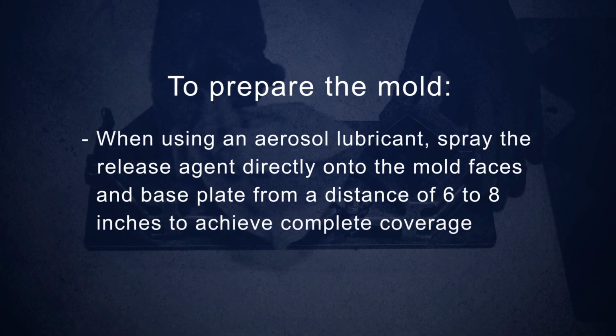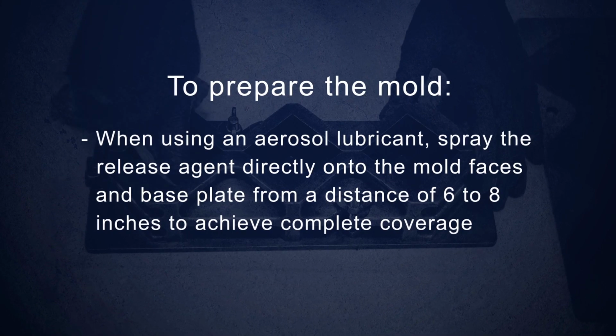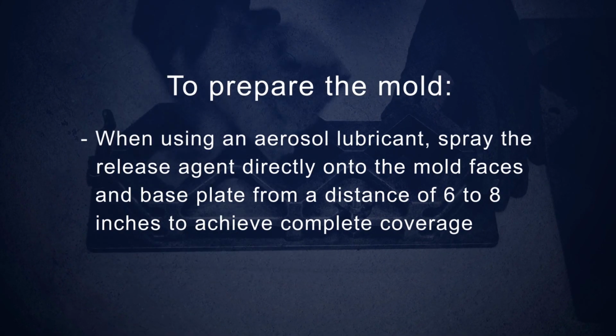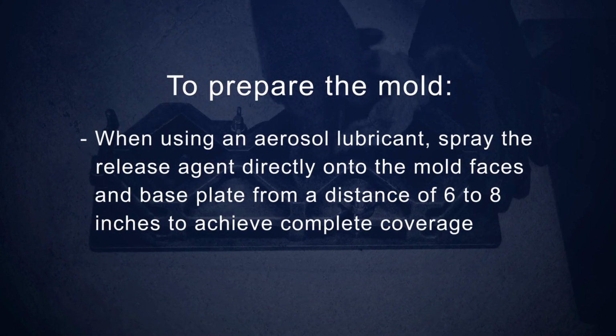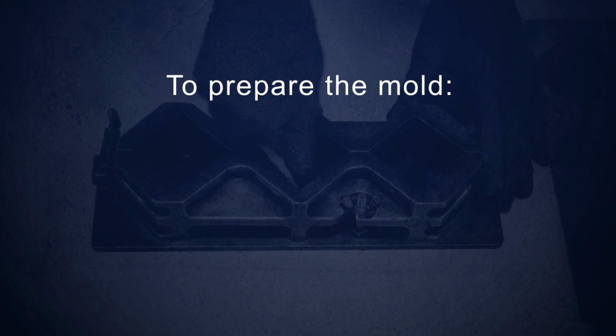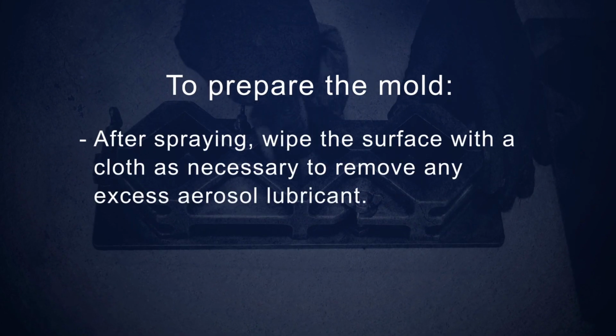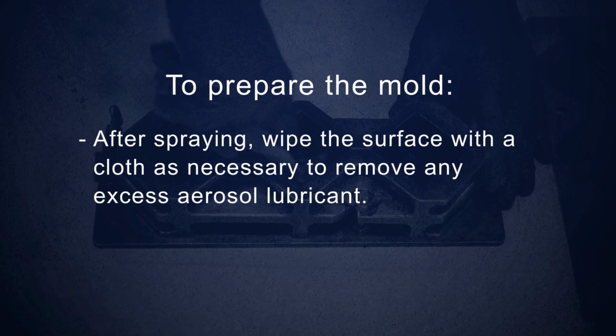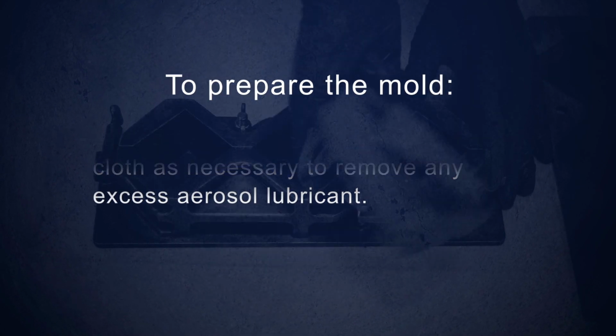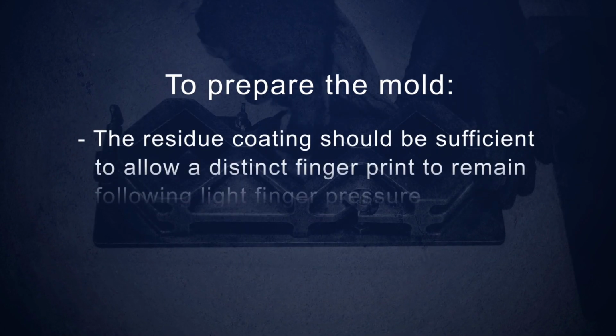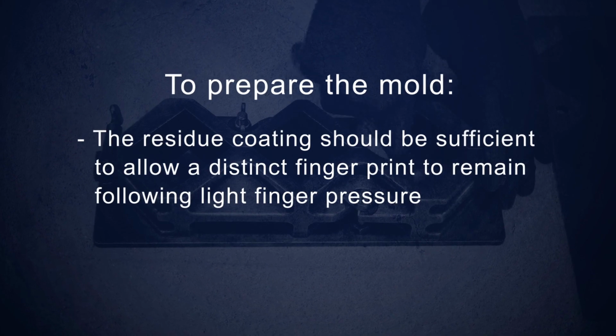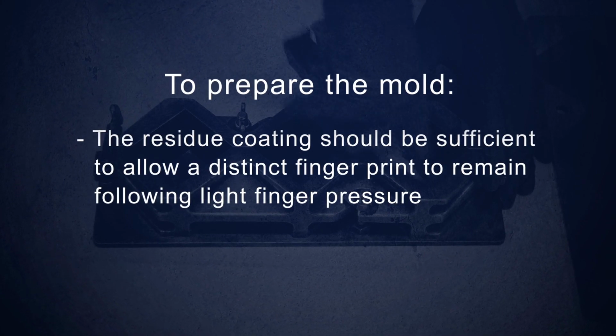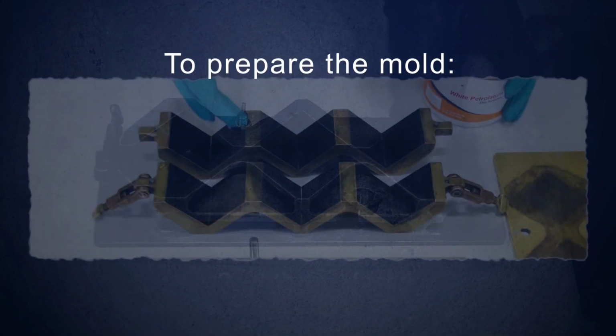When using an aerosol lubricant, spray the release agent directly onto the mold faces and base plate from a distance of 6 to 8 inches to achieve complete coverage. After spraying, wipe the surface with a cloth as necessary to remove any excess aerosol lubricant. The residue coating should be sufficient to allow a distinct fingerprint to remain following light finger pressure.